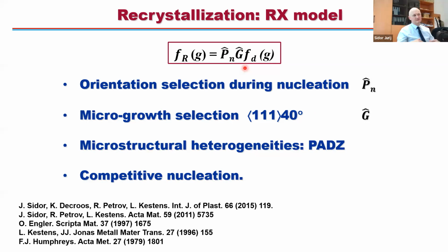If you remember at the beginning, I told that we should have very good knowledge about the deformed structure. So in fact, when you model the recrystallization texture, you should have very good knowledge about the deformed state. So we take deformation texture, then we apply growth and nucleation operators on this texture. So growth operator in our case is micro growth selection. We assign high mobility to 111 40 degree oriented grains with respect to the deformed structure, right?